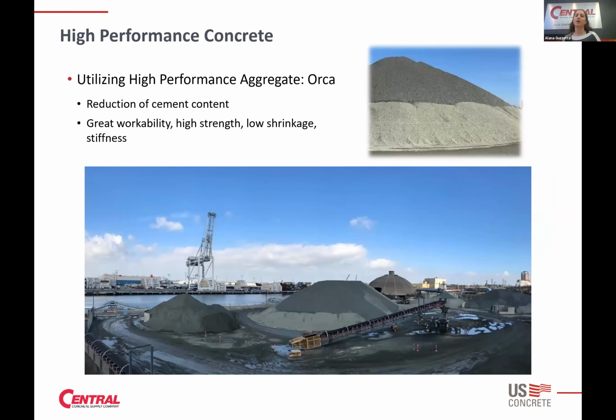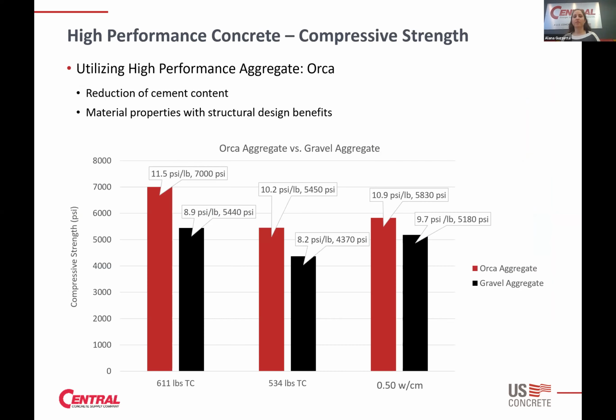A specific type of high performance aggregate is Orca. This is a US concrete aggregate that we have out of British Columbia, Vancouver. And this is an example of what we're able to do with that. So we're able to get cement efficiencies with this type of aggregate, and better efficiencies means that we can lower how much cement is in the mix. And if you recall from previously, the cement has the highest embodied carbon in the mix. So being able to lower how much cement content you need in the mix is going to further reduce the embodied carbon of your mix.